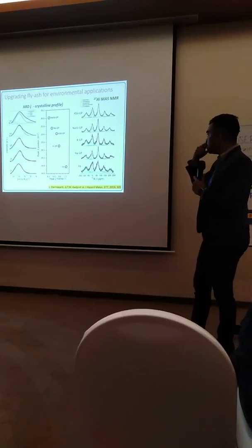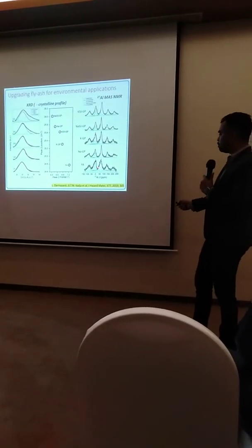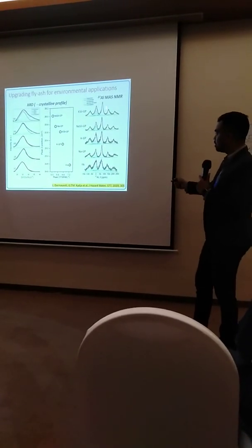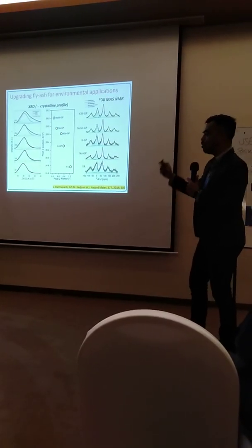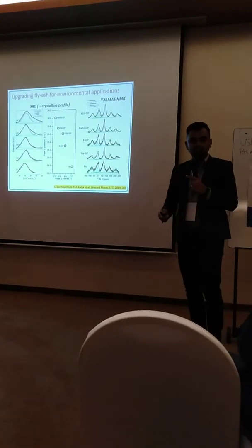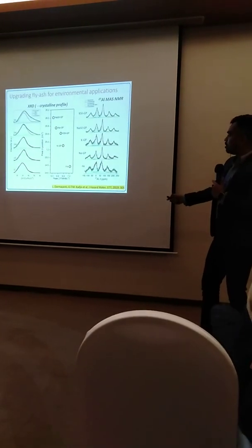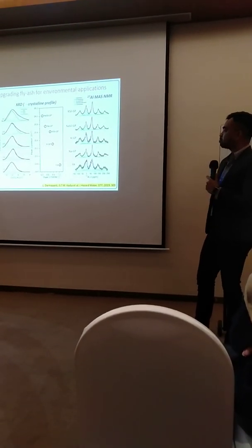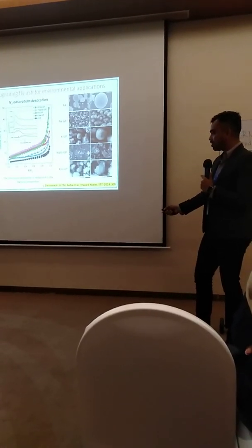It is also confirmed by the aluminum MAS NMR. You'll see the full width at half maximum, the disorder in MAS NMR, is the same as the order in XRD. So they are confirming each other. So there are structural alterations within these geopolymers. This structural alteration is actually reflected in the textural properties.